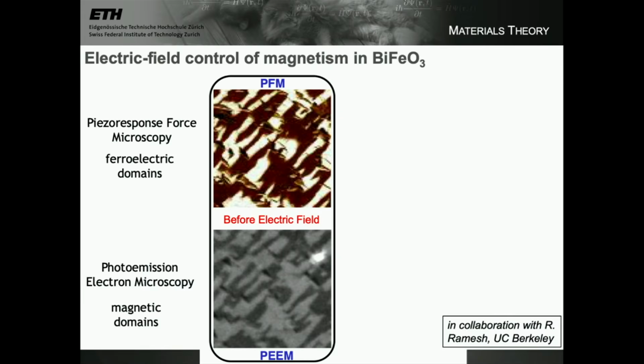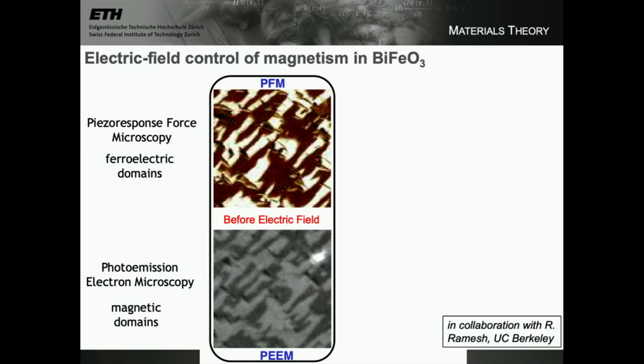So these are images, again, of bismuth ferrite. So this is the first multiferroic that I told you about, in which the magnetism is coming from the iron, the ferroelectricity is coming from the bismuth. And these are images of the same area before I do anything to them, before there's any electric field applied. And the top image is taken using a technique called piezo force microscopy, which is sensitive to the ferroelectric domains. So in the top image, the black and white regions are electric dipoles pointing out of the page or into the page.